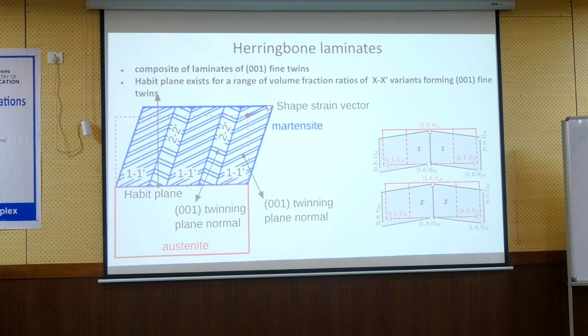So the conclusion, which can be easily accepted, is that if you have a single crystal of big grain size, you can have laminates with a spacing of maybe 100 nanometers because it's big. If you have a grain of 50 nanometer size, then how do you put a laminate with 100 nanometers into a 50 nanometer dimension? It is not possible. So the microstructure must be much finer. And for NiTinol it's very easy to make these 001 twins. I will show you by electron microscopy, every 5 nanometers there could be such a twin. So for NiTinol it's very simple to make such microstructures, but then the habit plane is constructed in a different way, but it can be constructed as well.